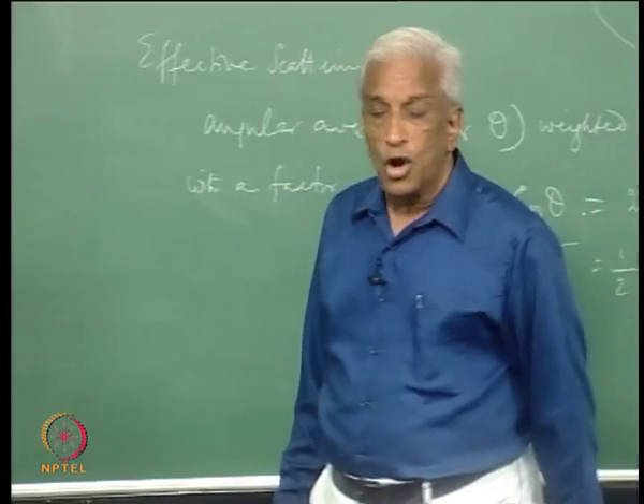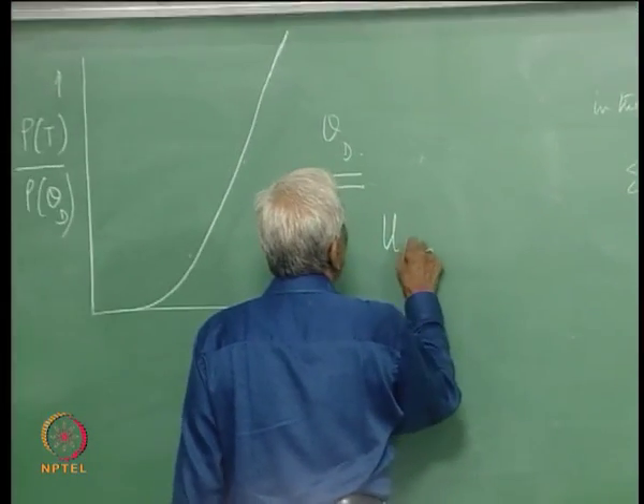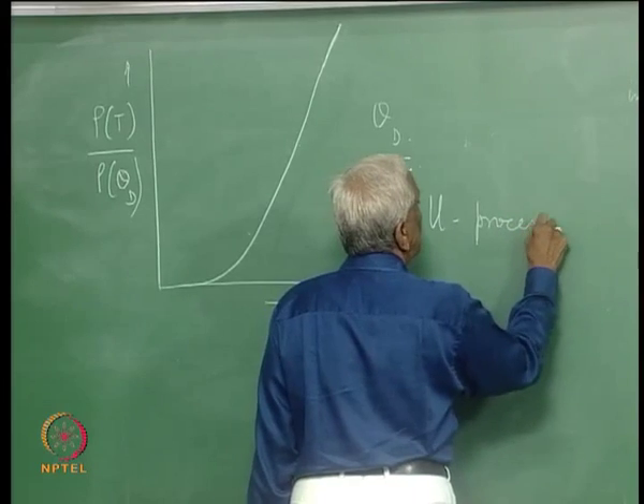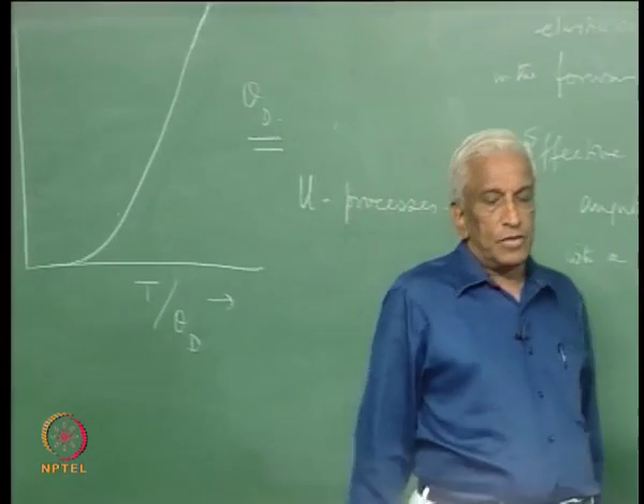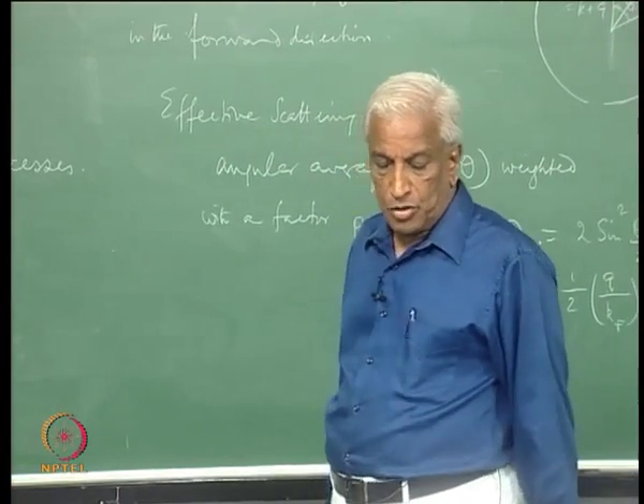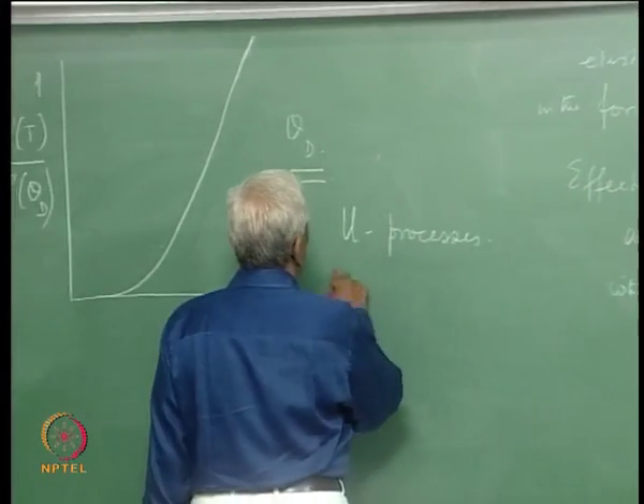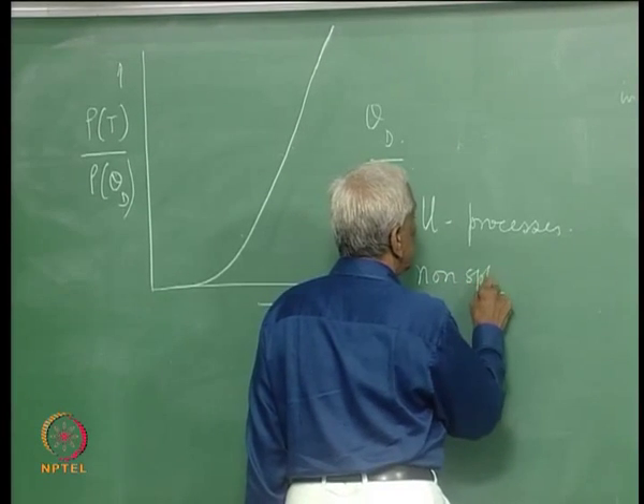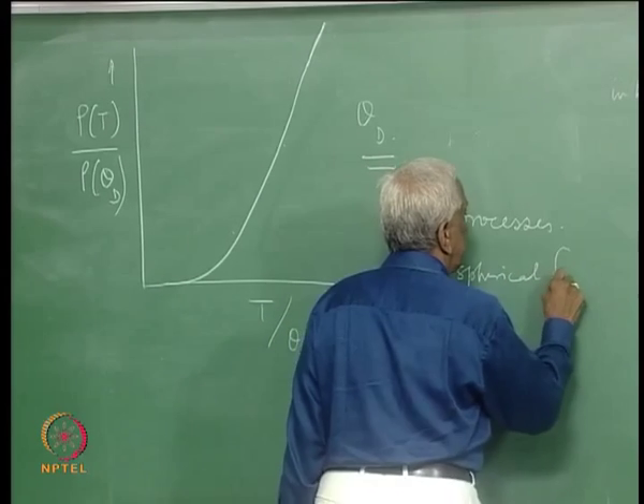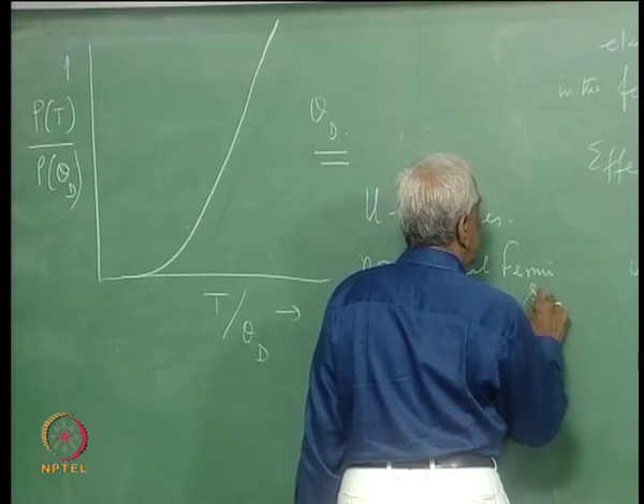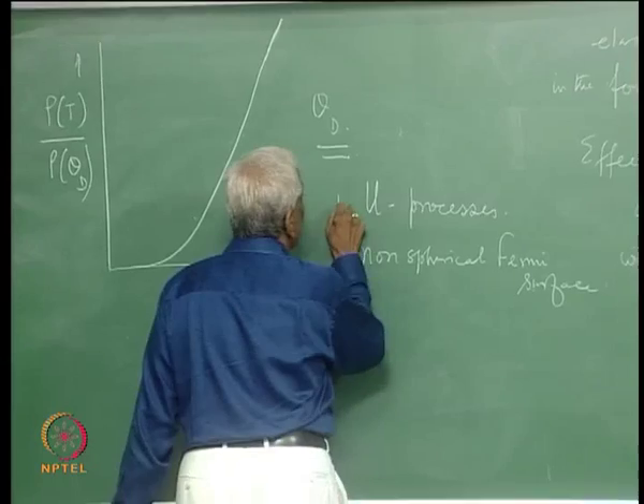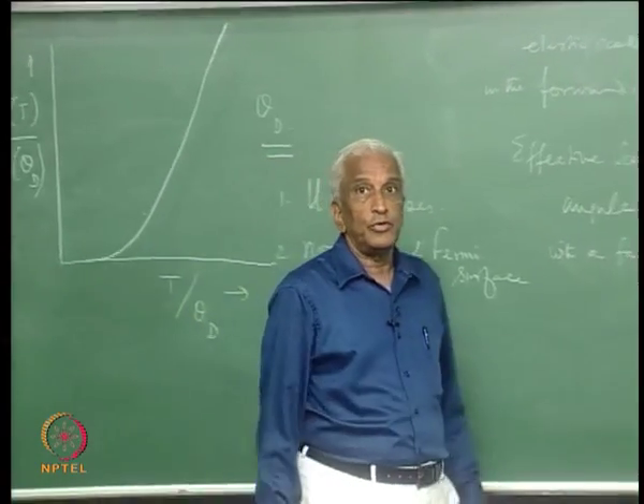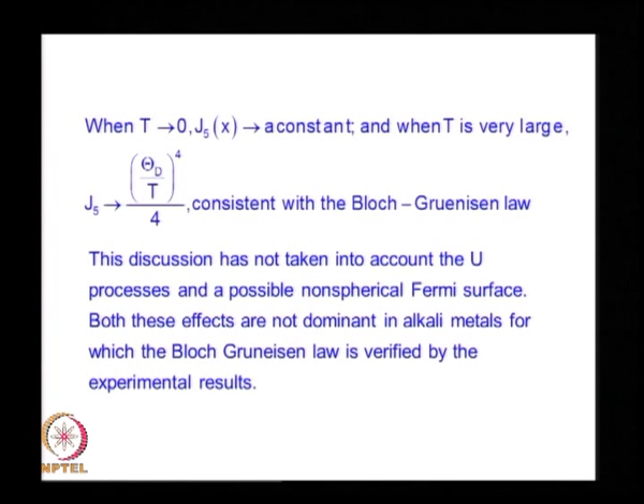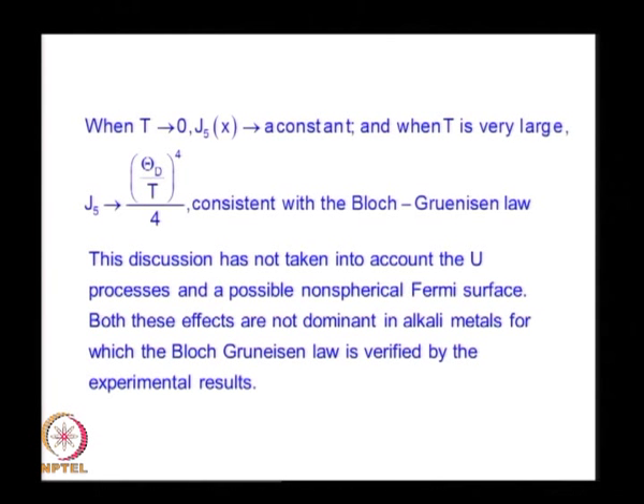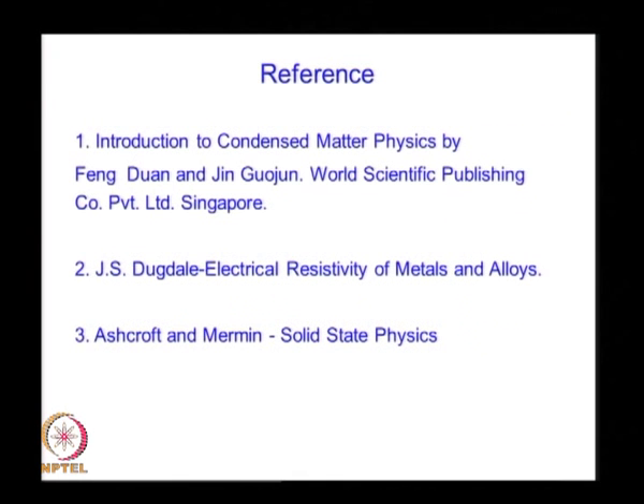However, this discussion has not taken into account Umklapp processes. We considered only normal processes, but as we know from the thermal conductivity discussion, Umklapp processes are quite important, and also a possible non-spherical Fermi surface. We have considered only an isotropic spherical Fermi surface. So, these are the two factors which have not been taken into account, but these effects are not dominant in the alkali metals for which the Bloch-Gruneisen law has been verified by the experimental results.